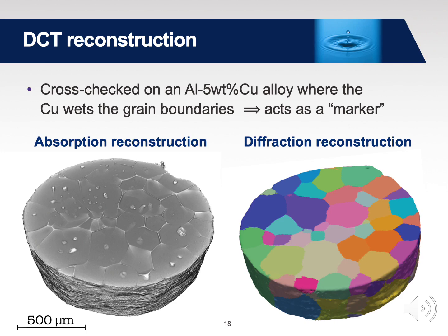And so in this particular absorption reconstruction, we're achieving the maps of the attenuation coefficient. So here, from the absorption reconstruction, we can map out where the copper sits, and if we know where the copper sits, then we can trace out these grains, and we can compare it to the diffraction-based reconstruction to determine, well, how good is the reconstruction of grain shape.